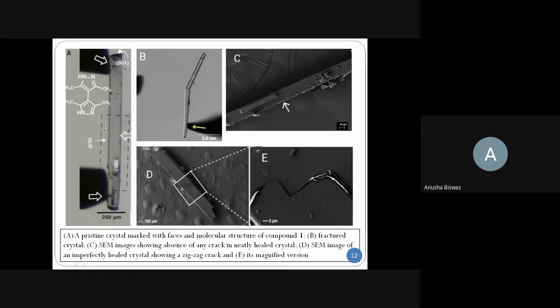This crystal is known as the pristine crystal. In this crystal, a crack is introduced. In this single crystal, it is a cracked crystal, and in this C, the crack is perfectly healed, and the crack marks also disappear. Therefore, it is a neatly healed crystal. But in the D and E crystals, the crack line is still visible even after the healing process. Therefore, it's an imperfectly healed crystal.